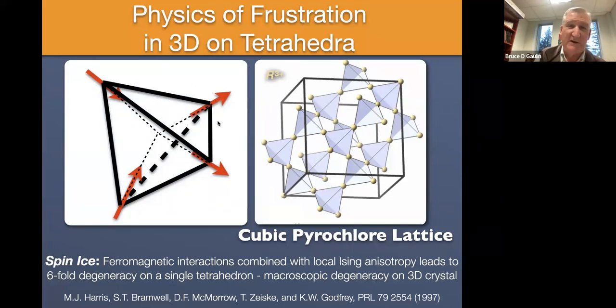So this is one particular combination, which might strike you as a little bit contrived, but as I'll explain, it's a situation that nature actually likes. We've got magnetic moments at the vertices of the tetrahedra, and crystalline electric field effects constrain these moments to point either into or out of the tetrahedra. So the magnetic moments have this easy axis, but the easy axes at the four sublattice positions on a tetrahedron are not parallel to each other. They're not collinear.